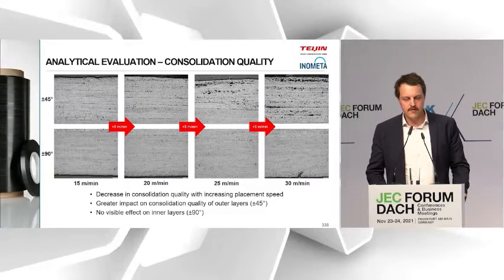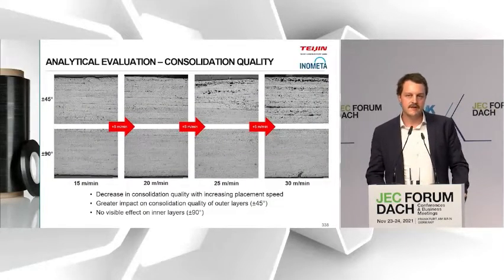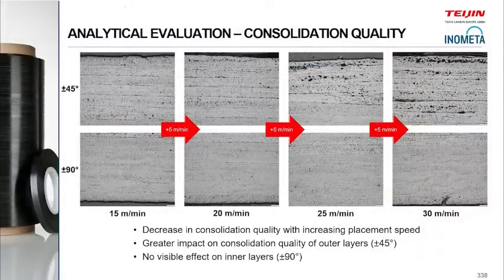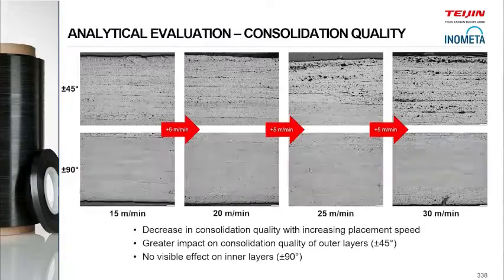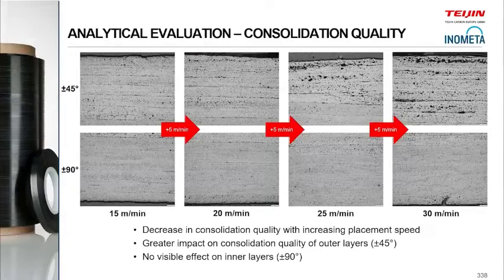So we did some trials and looked at how the consolidation quality decreased or improved with different setups. As I mentioned, we started with 15 meters and then added for every trial another 5 meters per minute. What you see here is the plus minus 45 that are the outer layers of the part. The plus minus 90 are in the middle. Below there is then the heated spindle that we use for the winding trials. And you clearly see, if you look into the plus minus 45, for example, with the increasing speed, a decrease in consolidation quality.